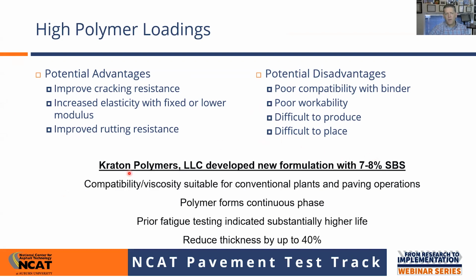And when we started talking with Kraton Polymers back in, I guess it was about 2008 or so, they had just developed a new formulation that used in the neighborhood of 7 to 8%. What we put on the track was a 7.5% SBS. Through chemical engineering and their knowledge and experience, they had overcome some of those disadvantages with workability. They had done some pretty extensive lab testing that showed this had a high potential for use in paving, but hadn't yet really built any significant projects with a lot of traffic on them. And notably down here at the bottom, the laboratory studies had indicated they could perhaps reduce the thickness by up to 40%. But as Buzz mentioned, and we believe strongly at the test track, the proof is in the road, and let's build a section and see what happens. And that's how we got involved with them initially back in the 2009 experiment.